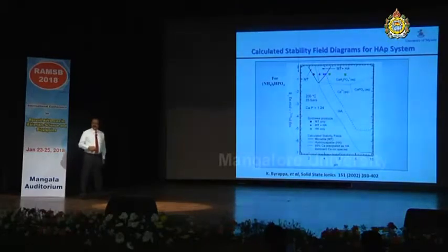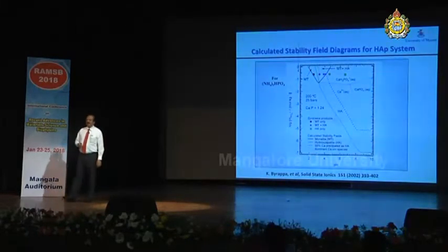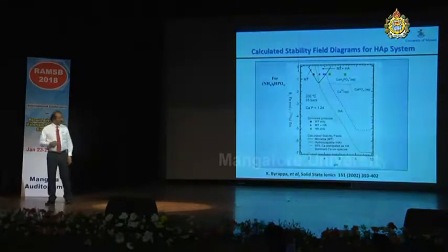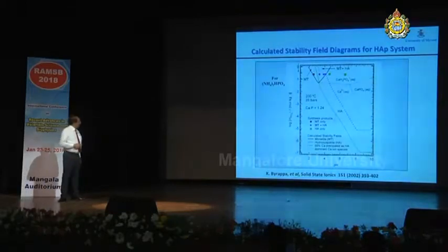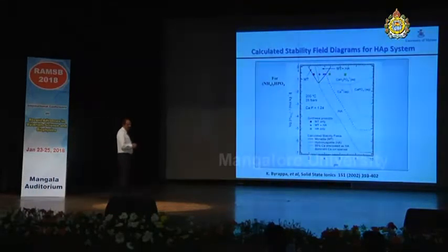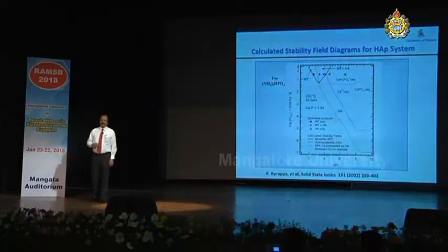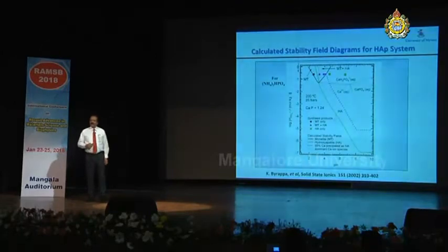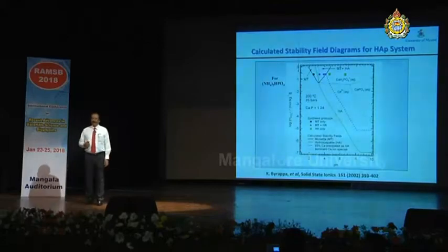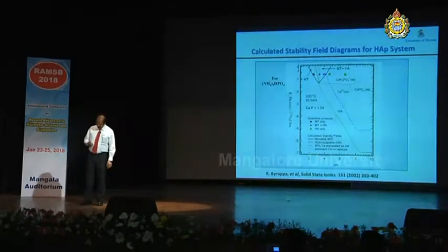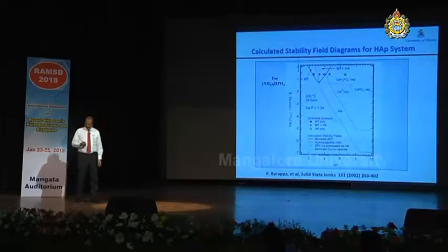Well, under hydrothermal technology, in recent years, instead of carrying out experiments on an empirical basis, and instead of carrying out hundreds or thousands of experiments, which people used to do in the earlier days, and at the end of the experiment after a very long period, if you take the example of quartz or ruby crystal growth practiced during the 1880s and 1890s, even after 3 months after carrying out the experiment in the hydrothermal autoclave, once the autoclaves were opened, they found nothing. The crystals didn't grow.